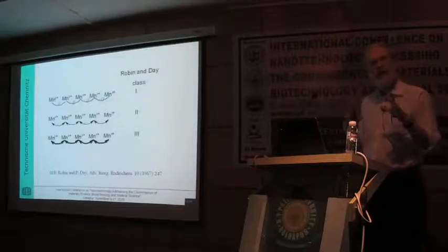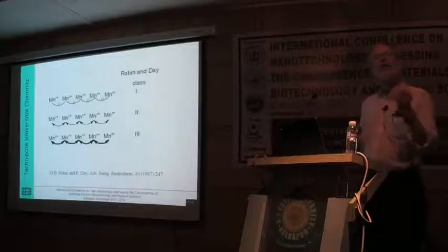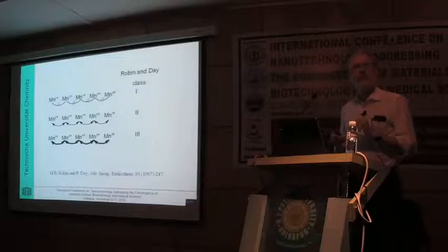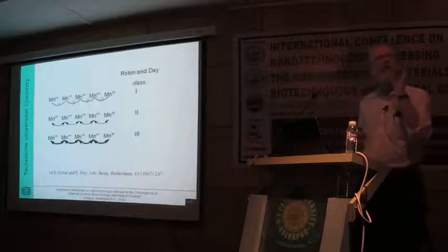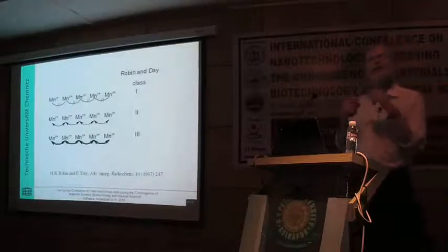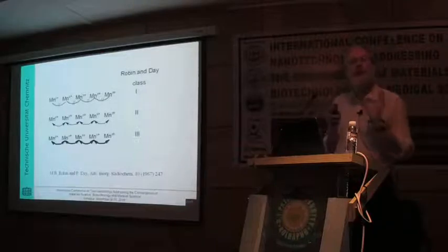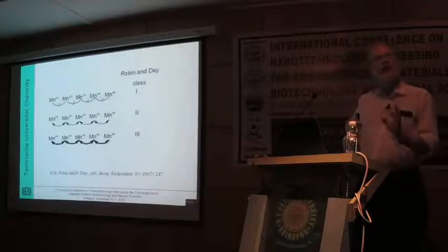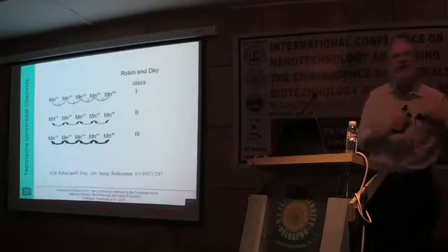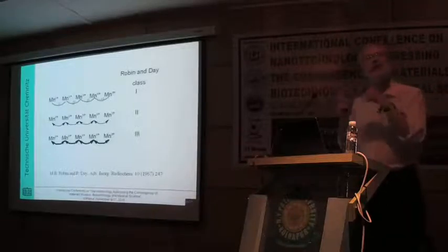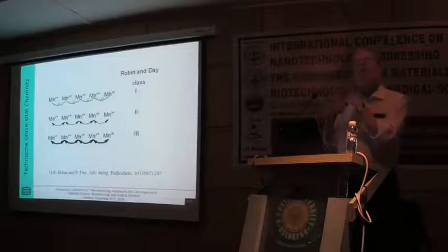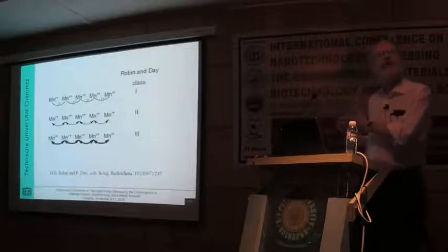4 surface, we have a huge number of manganese ions, and these manganese ions are more or less close to each other. If we start to oxidize, let's say, one manganese ion, this oxidation will happen at whatever electrode potential. I don't care about the number right now. If I now try to oxidize the next manganese ion, the first already oxidized manganese ion, which is now present as a manganese 4 ion, might affect the energy I need to provide to remove the electron from the neighbor.